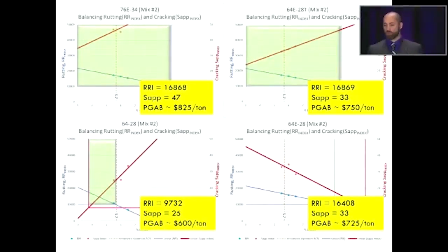And again, the cost associated with it, you do see an increase in crack resistance with the polymer modification in the SAP value. So that did capture the polymer modification better than the IDEAL CT, but it's a much more complicated test. And when something goes wrong, you have to go back and start over with a very complicated, long test.